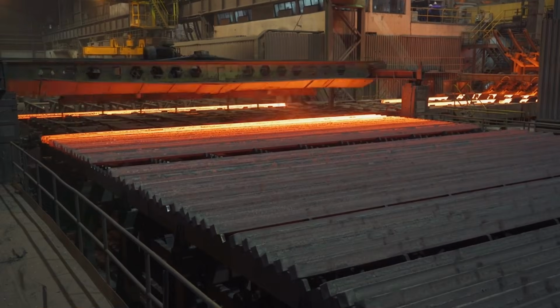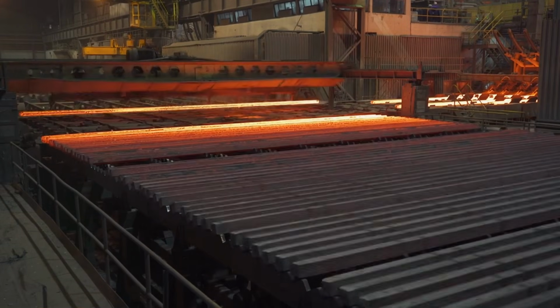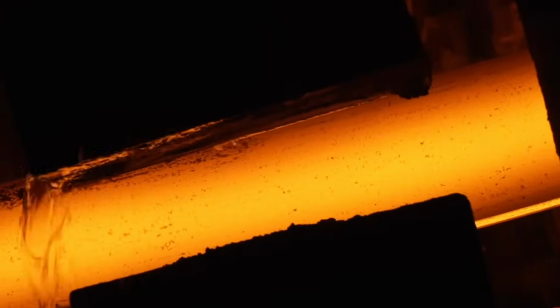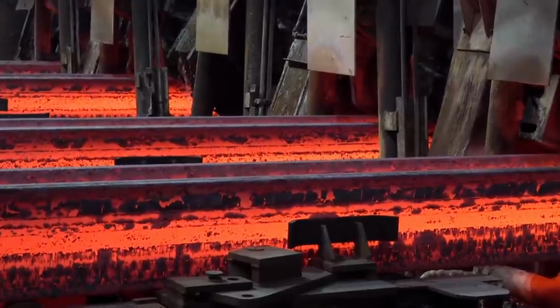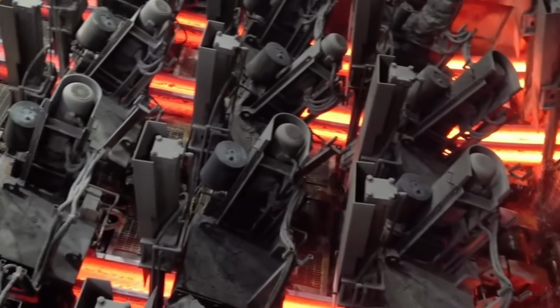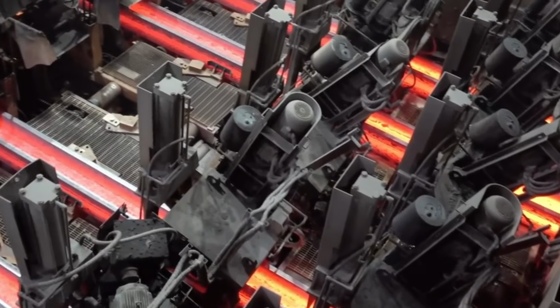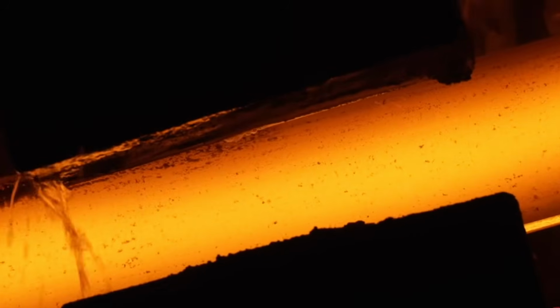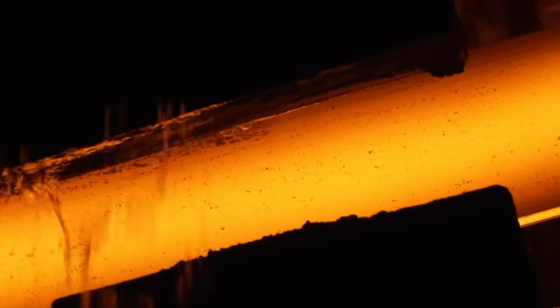The transformation from square to I-beam happens gradually. Early stands flatten and stretch, reducing thickness while increasing length. Middle stands form the web and flanges using specially grooved rollers. Final stands refine dimensions, ensuring the web is vertical and flanges are parallel, maintaining tolerance within fractions of an inch.